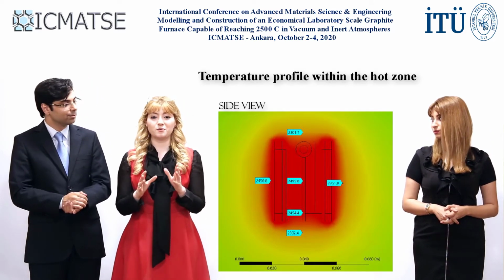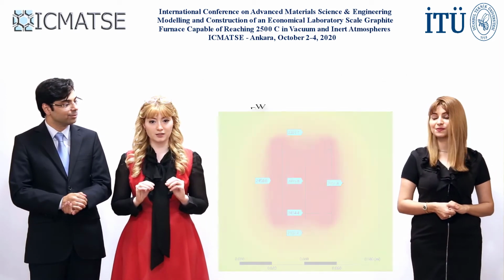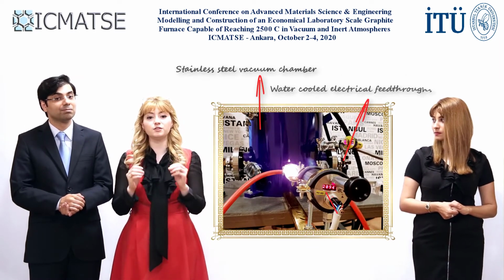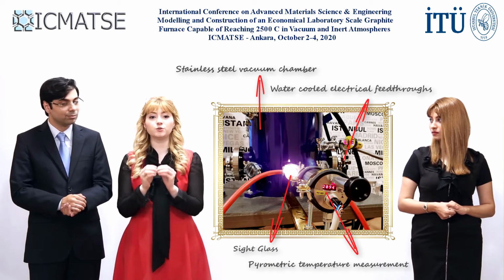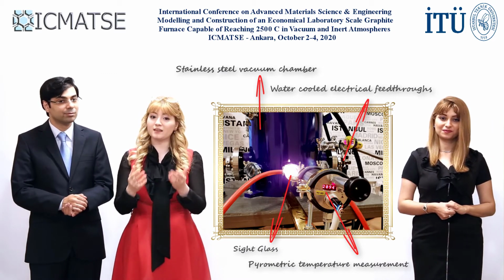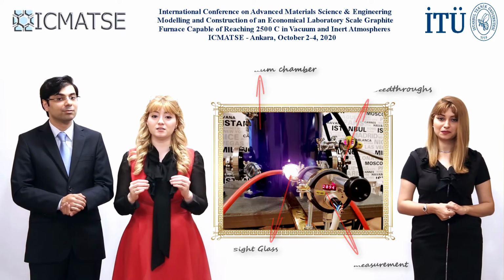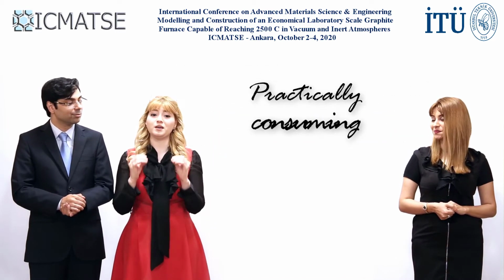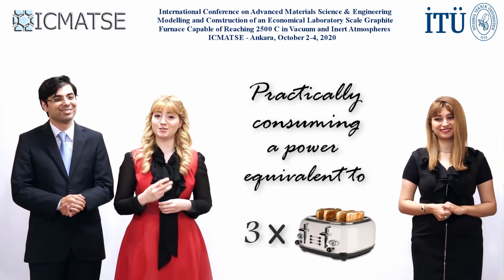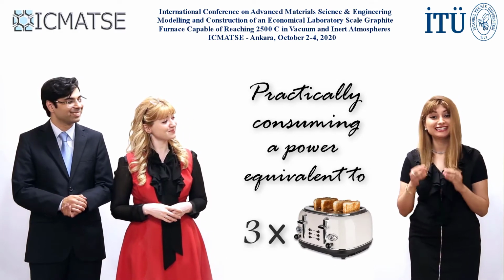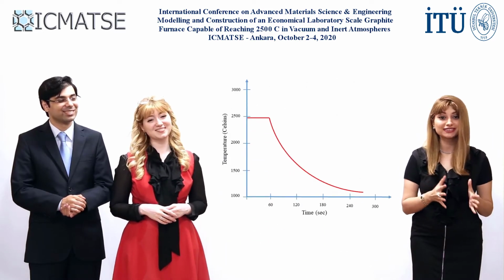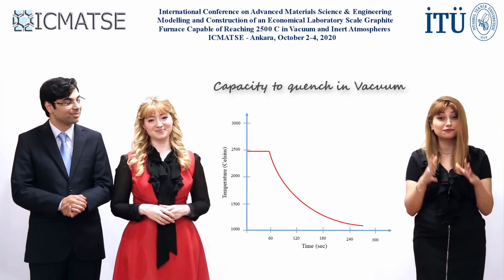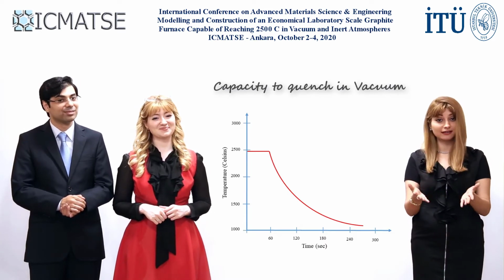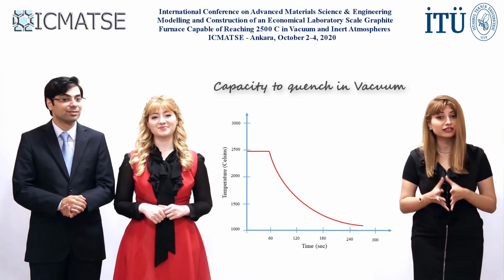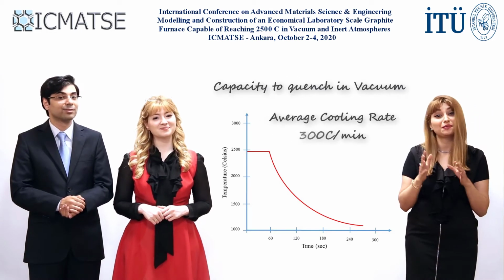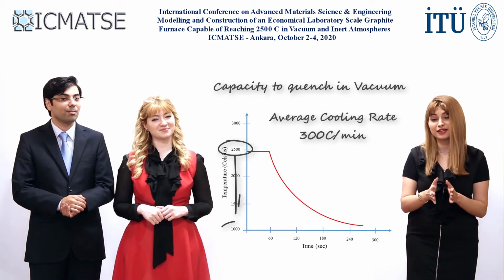The entire system works on single-phase alternating current, with the hot zone placed inside an ordinary vacuum chamber with two water-cooled electrical feed-throughs connected to a stainless steel chamber. And the entire system is practically consuming a power equivalent to 3 toasters. Another beauty of this design is that due to its size, the water cooling system has the capacity to cool it down very effectively if the power is disconnected. And we have seen an average cooling rate of approximately 300 Celsius per minute from 2,500 to 1,000 Celsius.